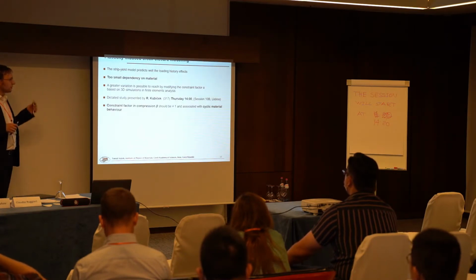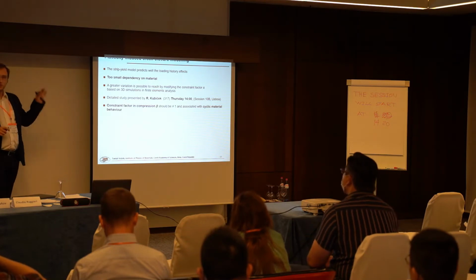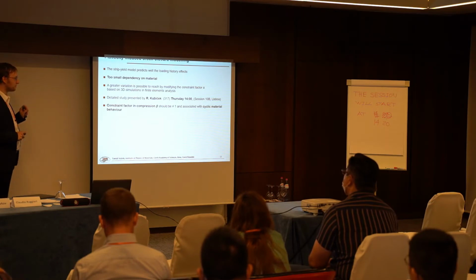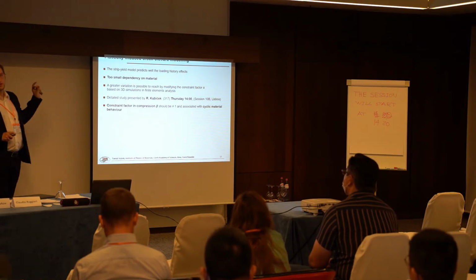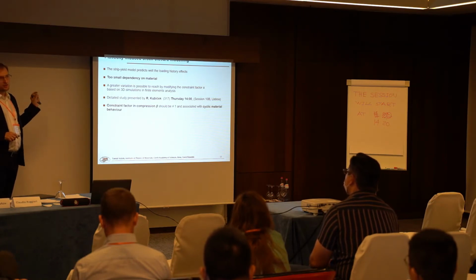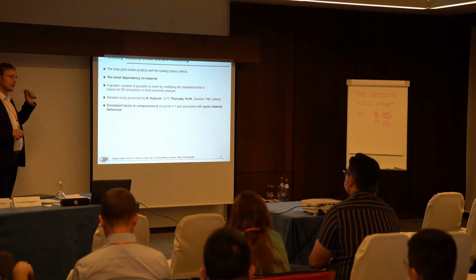And it does have a very small dependence on material. So it depends only on monotonic properties. So you put the limit stress, the ultimate strength, and even if you vary them, you don't reach big differences between the closure ratio predicted by the models. And it does not depend on cyclic material behavior at all.